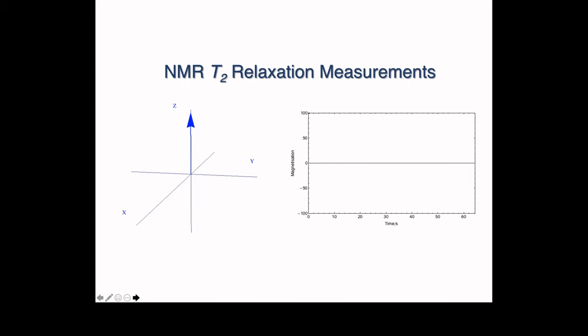So the T2 measurement, I just had this little video to show you how the T2 experiment works. I'm not really going to explain this, but you'll see it's quite a complicated business. So the spins precess and rotate around the XY frame. And what we see on the oscilloscope is a series of these called echoes, spin echoes. And when we have all the echo train complete, we take the heights of the echoes and we use those to get the NMR relaxation time. I haven't really explained that, but just to give you the idea, if we're looking, say, at water, which has a T2 of about 2 seconds, we'll probably generate something like 16,000 of these pulses. And we take the height from each of them, so we get a representation of the system.